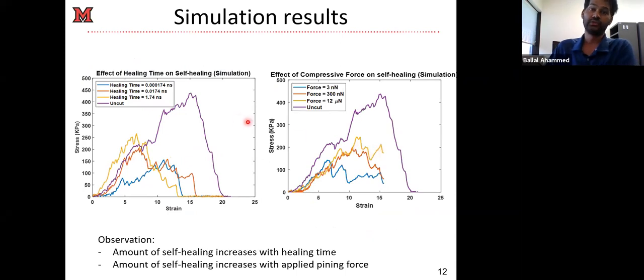Then we try to simulate and see what we get out of our simulations. We found a similar trend, but when we increased our healing time, in terms of peak stress, it recovers better. Although the behavior may be a little different from what we are seeing in the experiment, because we are using coarse-grained simulation, so we are missing a lot of atomistic details. It's no wonder we get the trend right, but we don't even expect our result to exactly match the experiments, because that's what you have to sacrifice when doing coarse-grained simulations and ignoring a lot of atomistic stuff.